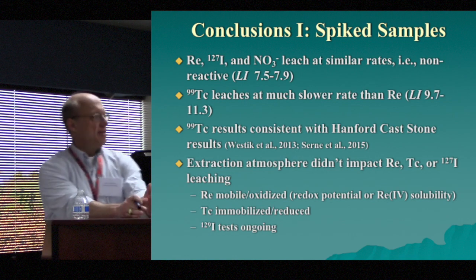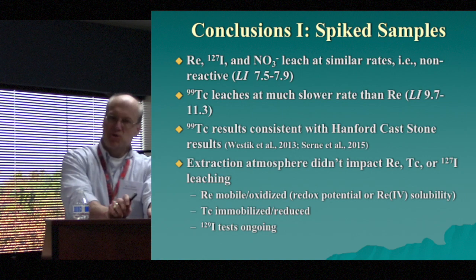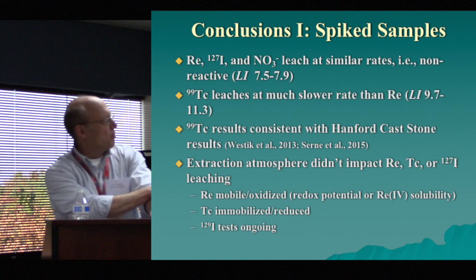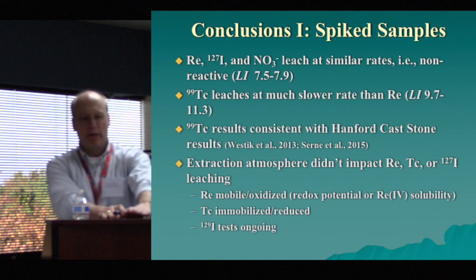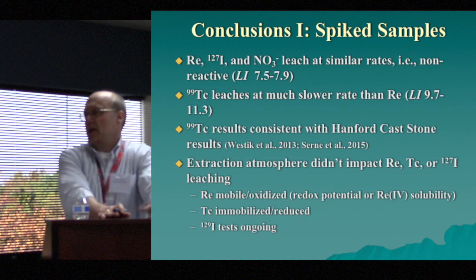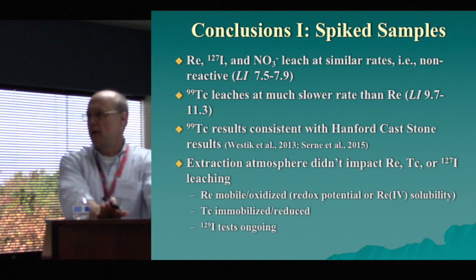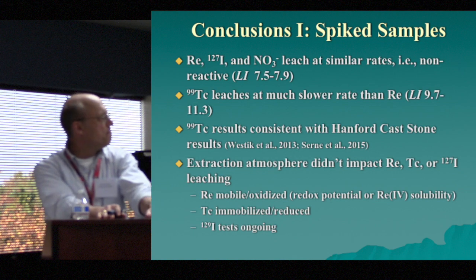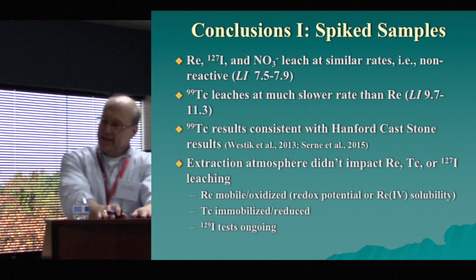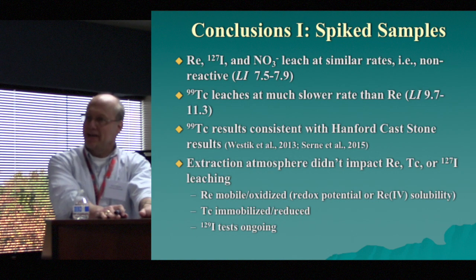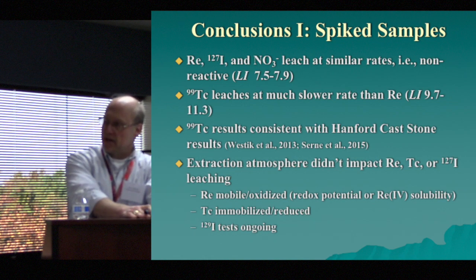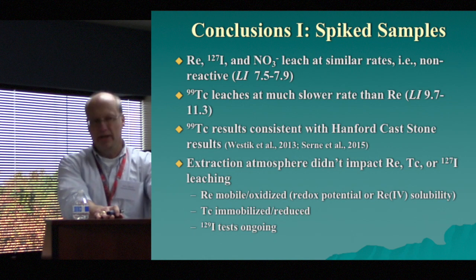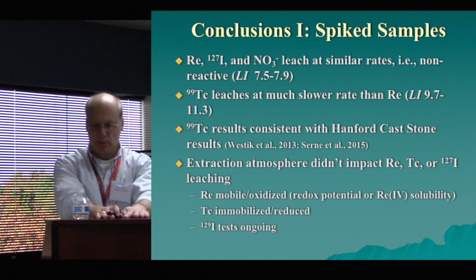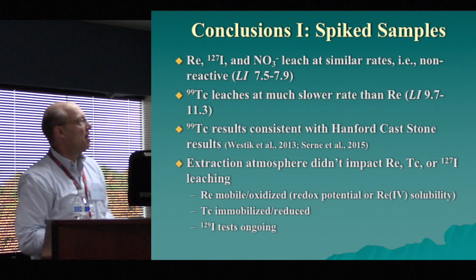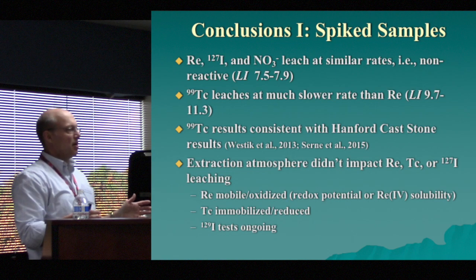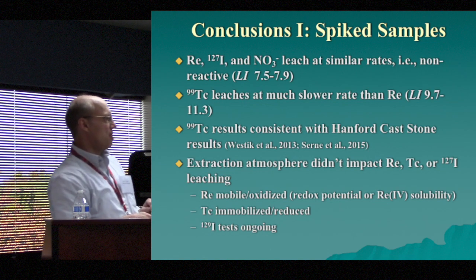And there are two different ways to try to rationalize this. The first way you could think of is that rhenium is so hard to reduce compared to technetium, and maybe we never even reduce rhenium. And so it doesn't really matter. It just comes out fast regardless. But compared to Tc, it seems like we are able to reduce technetium. And so we get completely different responses simply based on whether it's reduced or not.